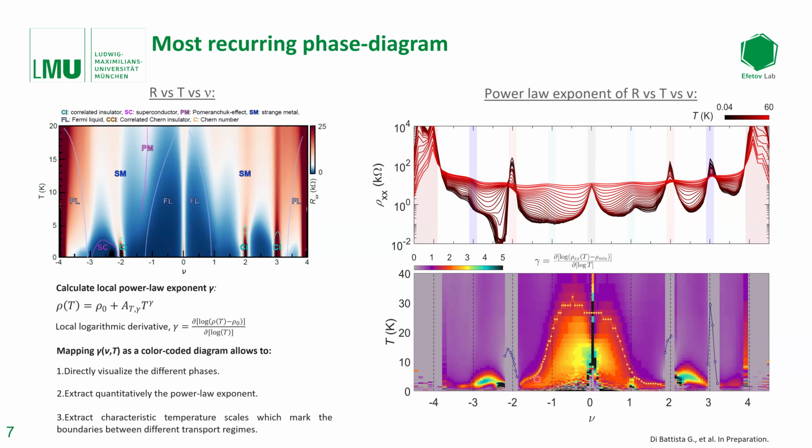Right. So for that instance, this is also a work in progress, and I'm happy to hear comments. If you look at filling factor -2, you see a strong asymmetry between doping on the electron side or the hole side. One of the most striking signatures is that the IVC order develops only on the hole side, and the superconductivity also develops only on the hole side. On the electron side, you get your Fermi liquid very quickly.